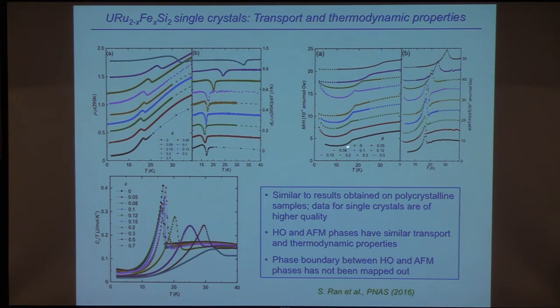And this is for magnetic susceptibility, basically the same thing. This is the derivative of susceptibility times temperature with respect to temperature versus temperature. So this kind of gives you what the specific heat should look like. And then this is actually the specific heat. So it's very sharp and large in the hidden order phase and smaller and more spread out in the antiferromagnetic phase.